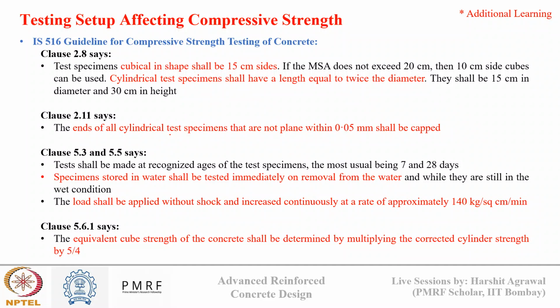And that's why we have standard provisions which are made to conduct compressive strength testing. So if you see, these are different clauses which are present in the IS 516 guideline for compressive strength testing of concrete. Different clauses specify different testing conditions. As an example, clause 2.8 says test specimens should be cubical in size of 15 centimeter side, and the maximum aggregate size should not exceed 20, and if it is not exceeding 20 then 10 centimeter side cubes can also be used.